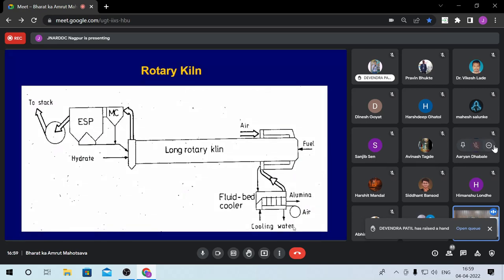So earlier there used to be a very long rotary kiln in which the fuel is fed from the right hand side, and the hydrate is fed from the other side. Slowly it rotates and the hydrate is heated, it loses its moisture and crystalline water, and the calcined alumina which is coming out at high temperature exchanges heat with air, and this air is then sent as hot secondary air for reducing the fuel consumption. The rotary kiln fuel requirement was around 120 liters per ton, and a lot of heat was lost through the external surface, so people went for